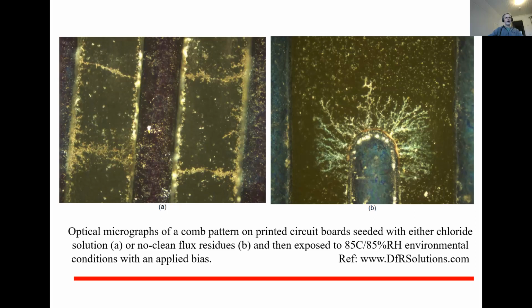So if these two lines are at different bias, 0 volts or ground and plus 5 volts, there is a short circuit in between. So this means that now the corrosion has not destroyed the actual material. This copper line here, the electrical resistivity or conductivity is almost identical to the as-manufactured one, because it might be 0.1 millimeter wide and 50 micrometers thick, and to form these kinds of dendrites we have only consumed less than 1 micrometer from the surface. So basically, from the bulk resistivity, we don't see any effect. So this corrosion has not affected the material itself, but it has destroyed the functional system by forming these short circuits.